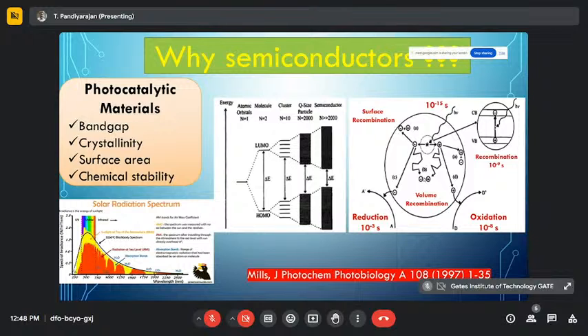If you see the time scales, the creation of this electron hole pair is on the order of 10 power minus 15 seconds, while the recombination process is 10 power minus 9 seconds. Suppose you can effectively harvest this electron hole pair separately, then the reduction process will happen on a time scale of 10 power minus 3 seconds, whereas the oxidation process will take 10 power minus 8 seconds. So this reduction and oxidation process will help convert your organic molecule into usable chemicals.